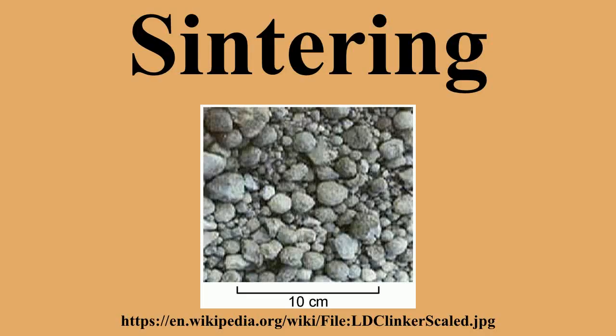Two-step sintering uses two different sintering temperatures. The first sintering temperature should guarantee a relative density higher than 75% of theoretical sample density. This will remove supercritical pores from the body. The sample will then be cooled down and held at the second sintering temperature until densification is completed.